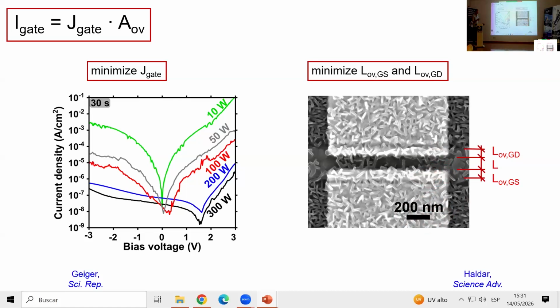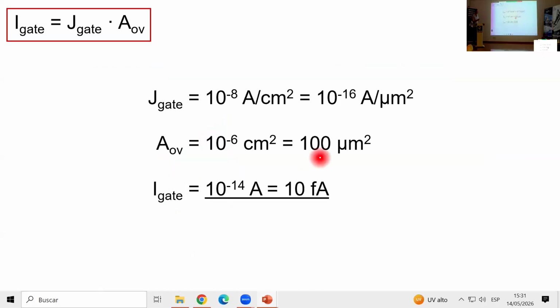And so for these particular values, again, the current density is on the order of 10 to the minus 8 amps per square centimeter, as I had shown. And when we make the overlap area on the order of 100 square microns, that gives us an absolute gate current on the order of about 10 femtoamps. And that happens to be the resolution limit of the measurement setup that we use in our lab. Okay, so it turns out that at the current state of affairs, we're right at the resolution limit of what we can measure. So even if we were able to make further improvements in reducing the offstate drain current, we wouldn't be able to measure it because it would be below the limit.